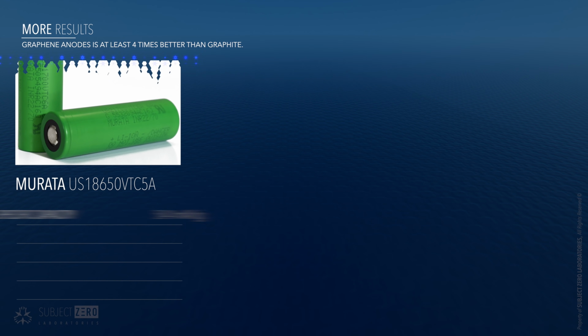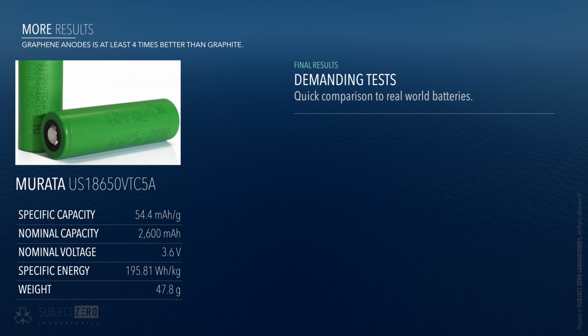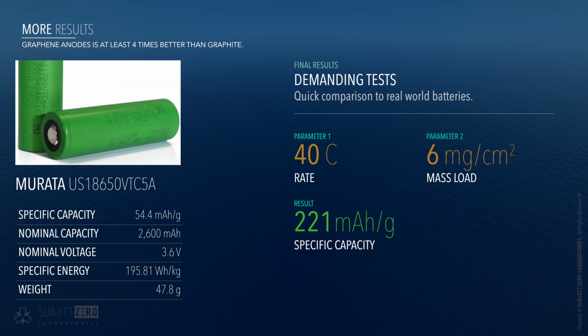More tests were conducted in other scenarios, and the results were, at worst, still 4 times better than graphite electrodes. Just to extrapolate things a little bit, the Sony Murata battery has a nominal specific capacity of 54.4 mAh per gram. When HNMG was submitted to its most demanding experiment with a high charge-discharge rate of 40C and with a mass load of 6 mg per centimeter square, it still provided 221 mAh per gram, which is almost 4 times higher than that of the battery nominal specific capacity.